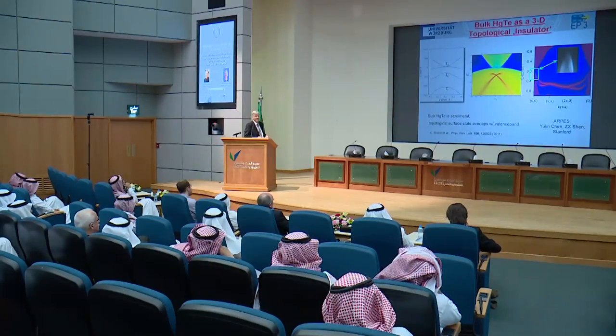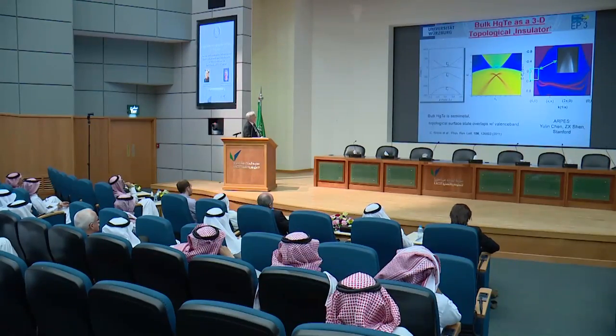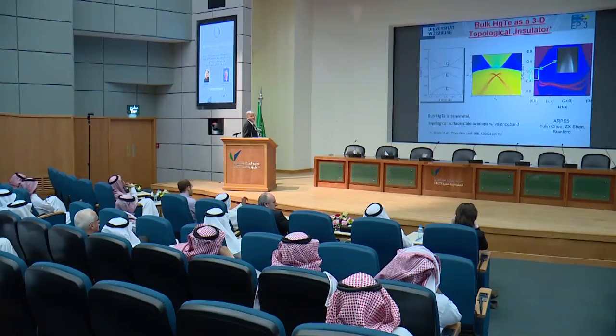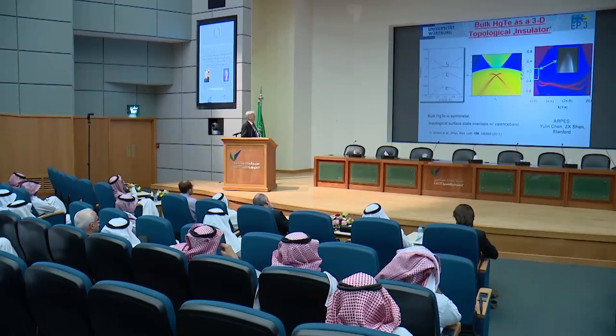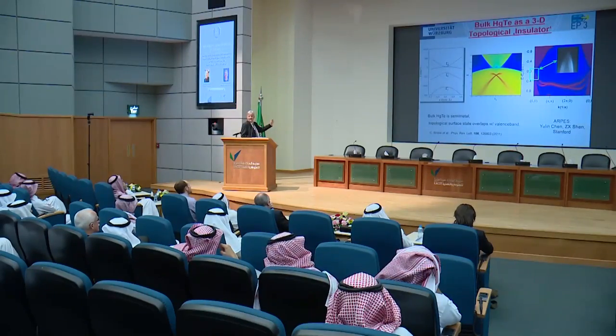Actually, these surface states have Dirac dispersion. And this is what you see here. Again, this is the band structure of bulk mercury telluride. And what you see here is this surface state, this topological surface state on top of the material. These are two DFT calculations. This is an actual experiment which was done by colleagues at Stanford University. Now, this is still in this bulk material where I have this semi-metallic band structure of the gamma 8 bands touching each other.